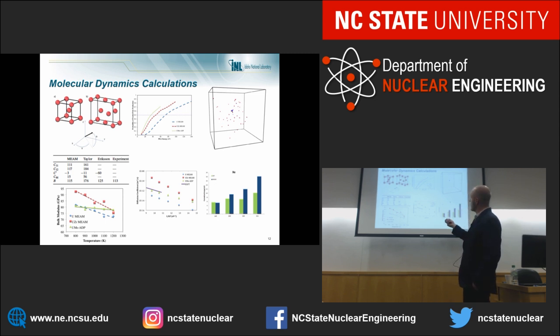So in this curve, we have our probability of Frenkel pair formation as a function of the energy, and we are defining the threshold displacement energy essentially where the probability becomes greater than 0.5, so that it's probable to create a defect in these systems. So for the original uranium modified embedded atom method potential that we made, it yields one number.